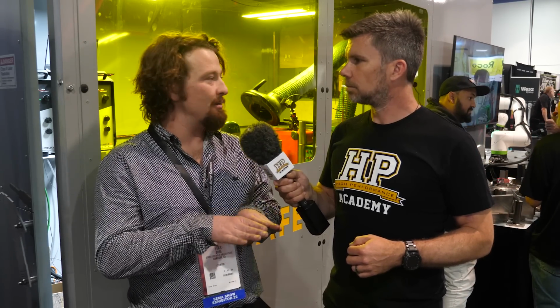Now, normally if we were maybe MIG welding or even TIG welding 1/4 inch plate, it's going to require quite a bit of prep work on the weld area. We're going to probably have to chamfer or V out that weld so we can get that full penetration. What's the preparation required with a laser welder? So with the laser welder, the best bet is to make the fit of the joint as tight as possible. We don't need a bevel and we don't need a gap. The laser has no problem penetrating deeply into the material. That's what it specializes in. And so we can just have a complete butted up joint and get full penetration right through. Even in the middle of a plate where there's no joint, I can penetrate all the way through.